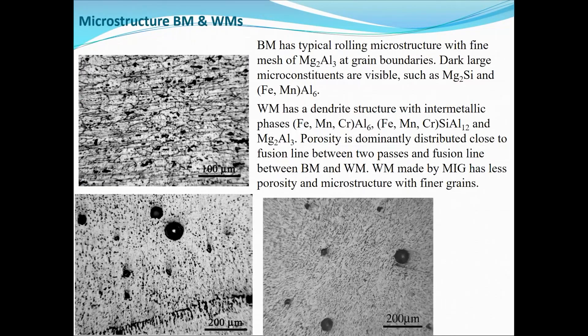These are typical microstructures for this material. You can notice a rolling direction and also certain intermetallic chemical compounds at the grain boundaries. The two microstructures presented below differ: to the left is TIG, to the right is MIG, and you can see at once that MIG has less porosity.